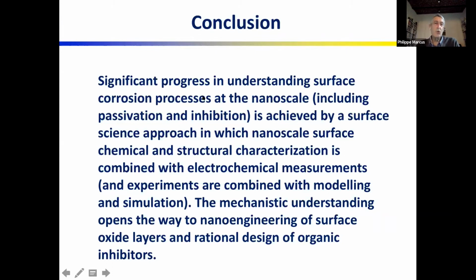So just a general conclusion: significant progress in understanding surface corrosion processes at the nanoscale, and I should say also at the nanometric and molecular scale, and that included passivation and inhibition. And that can be achieved by a surface science approach in which the surface chemical and structure characterization is combined with electrochemical measurements. And although I have not shown that today due to lack of time, this is very often combined with modeling and simulation.